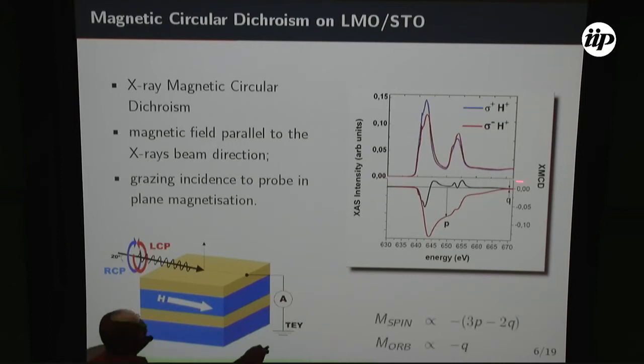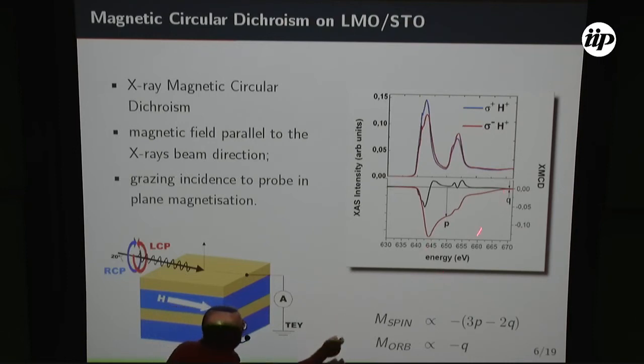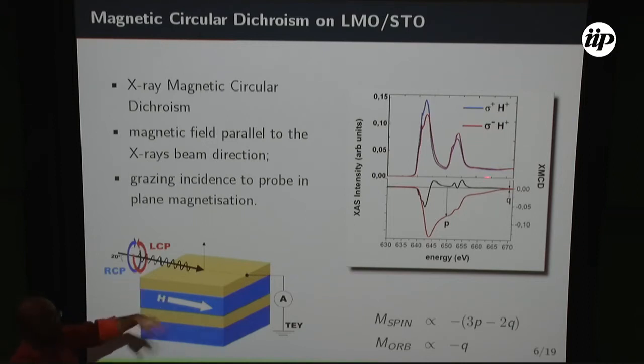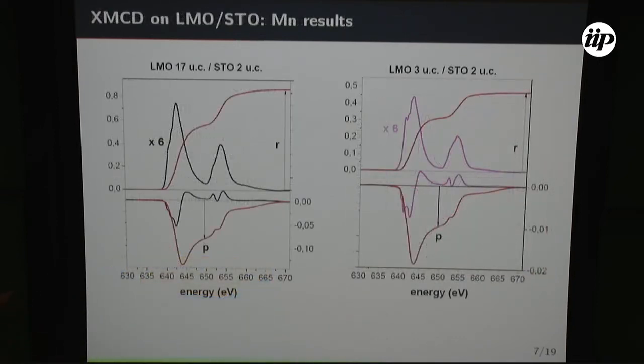For example, here, the integral at the end of the spectra is directly proportional to the orbital moment. So here I know that the orbital moment in this case is completely quenched. It's 0. If it wasn't 0, I could not tell you exactly how much it was, but as it's 0, I know that it's quenched. I cannot tell much about the spin moment. The only thing, with this value of the middle of the integral, I know that it's aligned with the field. This I know. So this is for the two extreme samples. They have very similar behavior, 0 orbital moment.